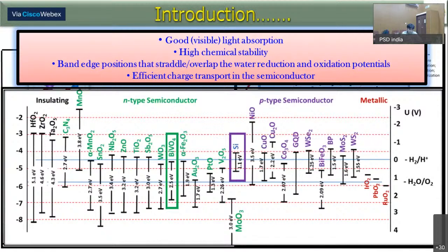Now, if you look into the literature towards the available materials, in the N-type semiconductors, bismuth vanadate is one of the most suitable materials, which has a very suitable band gap and band edge position. If you can see, the conduction band position is near the hydrogen reduction potential. So with this, we can get very efficient water splitting for hydrogen generation. That's why we have chosen bismuth vanadate in our study and carried out several water splitting experiments.